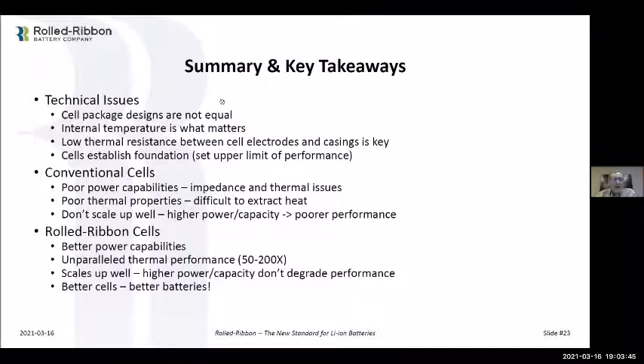So when you look at roll ribbon, kind of the key takeaways about all of that. So the technical issues are cell package designs are not all the same. The internal temperature is what really matters. Again, you gotta keep your eye on the ball. It doesn't matter what the external package is, but if the external package is hot, the inside's always hotter. In fact, temperature gradient inside to outside on a roll ribbon cell is less than 5 degrees C. A typical cylindrical pouch or prismatic will be 20 plus degrees C difference between inside and the outside. Low thermal resistance between the cell electrodes and a casing is the key. That's what we do. By making that edge of the electrode in contact with the actual external surface of the cell can, which is low thermal resistance, I can extract heat very, very quickly.